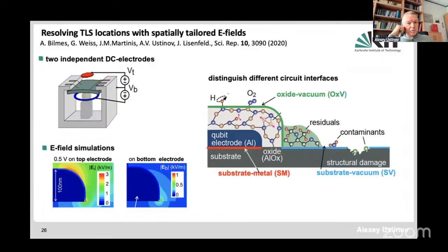In order to distinguish between the different types of surfaces, we came up with the idea to apply simultaneously two different DC voltages, one from the top of the substrate and the other from the bottom of the substrate. In this case, we can make an electric field simulation, calculating the field distribution in this kind of generic geometry where we have the edge of the superconducting electrode. This is basically this area here. When we apply the electric field from the top electrode, we see the field intensity distribution shown in color on the left. And when we apply it from the bottom electrode, we have another distribution, which is shown here on the right.